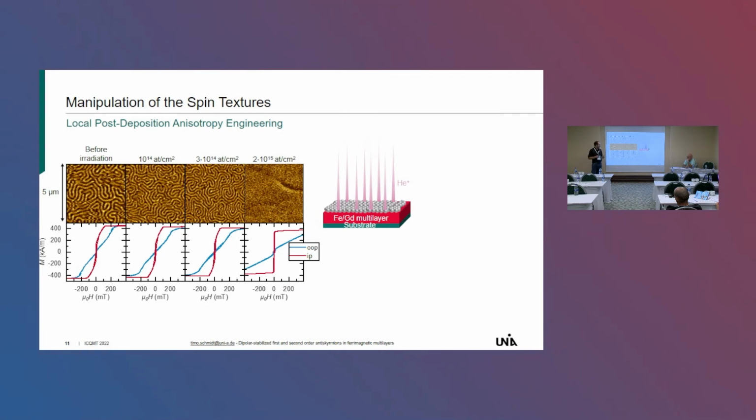And you can guess that the helium irradiation can't transfer through the nanospheres, so it only gets in between the nanospheres, and you only destroy the area where you don't have your nanospheres. And then if your nanospheres are approximately the size of your skyrmions, you basically have a hole where these skyrmions can form in, and outside of that hole there are forbidden regions for them.